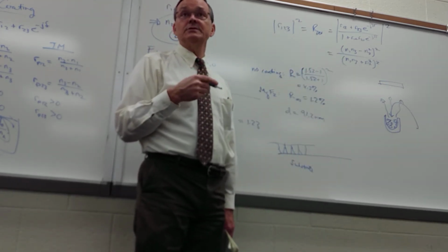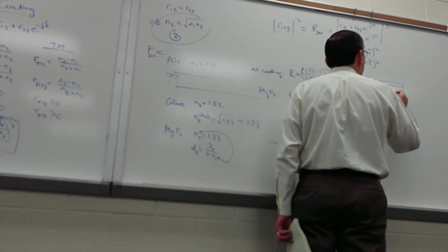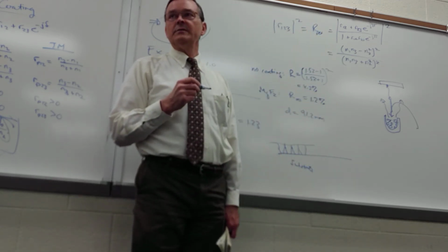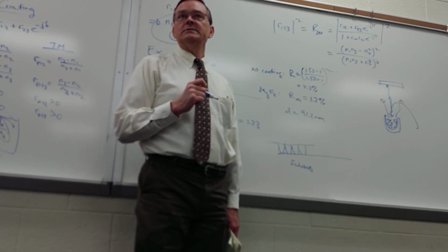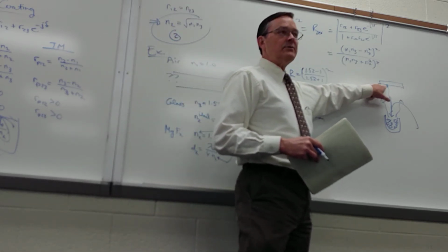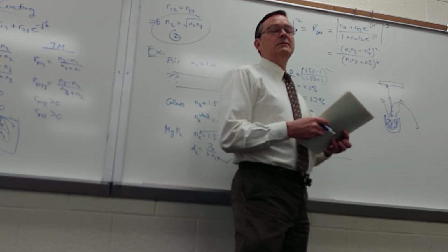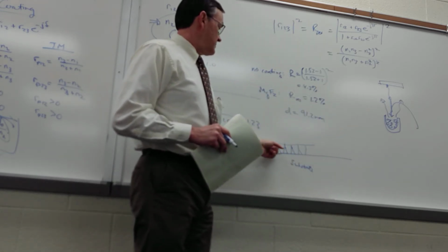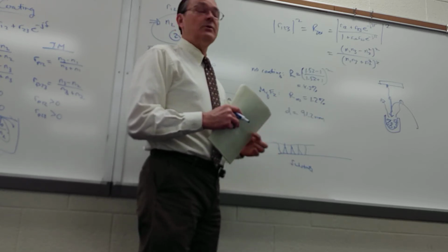And the substrate, in comparison, is quite cold. And so what happens is the molecules will come down, and they'll pretty much just stick wherever they hit because it's a cold surface. And what you want is to add some energy so that the molecules, when they stick, they're not really stuck, but they can move around and get to a location where they can minimize their energy, which gives you a much more dense film morphology. And so how do you do that?